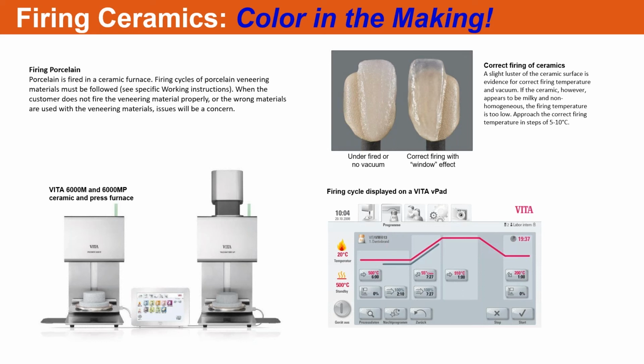So if you do any other types of materials inside your press furnace, make sure you periodically purge or clean that furnace. We traditionally do 1,000 degrees, 15 minutes, no vacuum for what we call a cleaning cycle for the muffle, and that pretty much cleans everything out of that muffle, any contaminants and so forth.